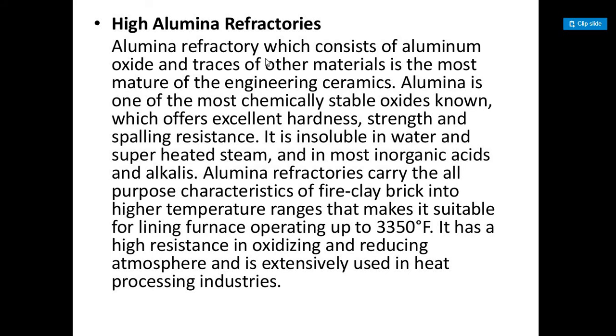High alumina refractories. Alumina refractory, which consists of aluminium oxide and traces of other materials, is the most mature of engineering ceramics. Alumina is one of the most chemically stable oxides known, which offers excellent hardness, strength and spalling resistance. It is insoluble in water and superheated steam and in most inorganic acids and alkalis. Alumina refractories carry the all-purpose characteristics of fire clay brick into higher temperature ranges that makes it suitable for lining furnace operating up to 3350 degrees Fahrenheit.